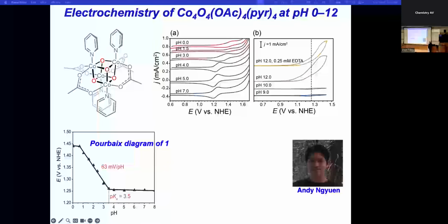So at neutral pH, you see a nice reversible wave for the oxidation of this cube. And the interesting thing right away about that is that that means you can access something that's formally cobalt 4 in the system. Now, you might not have an isolated cobalt 4. I'll come back to that. But it means that you're getting to an oxidation state that's unusual in isolated cobalt species. The Pourbaix diagram shown here indicates that this species is protonated in solution, and the redox chemistry and potentials are reflecting an equilibrium involving protonation. We know that pretty well now. We have a crystal structure of the protonated species itself.